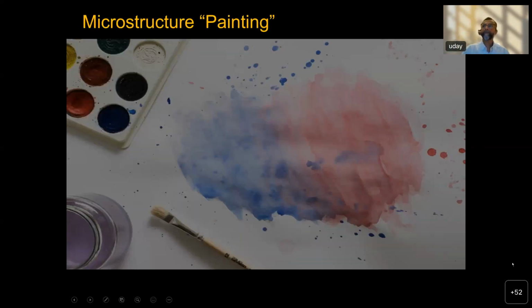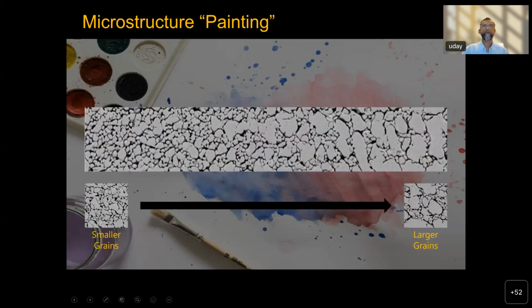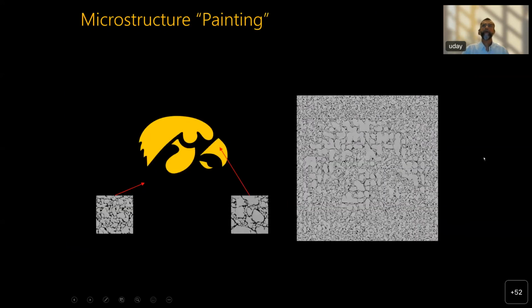We can also paint microstructures using this approach, which is to say that we can spatially vary the microstructure. So this is microstructure that was generated with small grains on one end and large grains on the other end. So we can do that. We can also paint microstructural regions. So here we have taken the Hawkeye, which is the University of Iowa symbol, and we've gotten permission to do that from our university, which is very important. And what we show here is that we want to put large crystals in this yellow region and small crystals in the black region. So we imprinted that Hawkeye image onto this microstructure. If you can see here, these are the large crystals, and then the surroundings are small crystals.